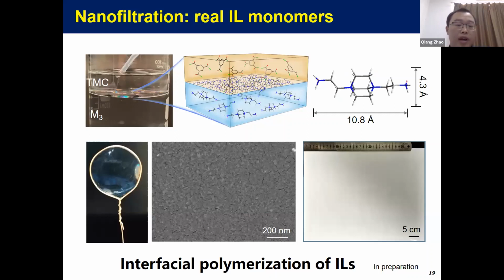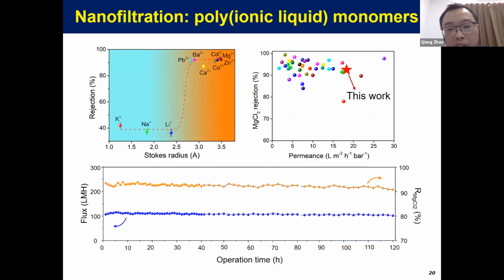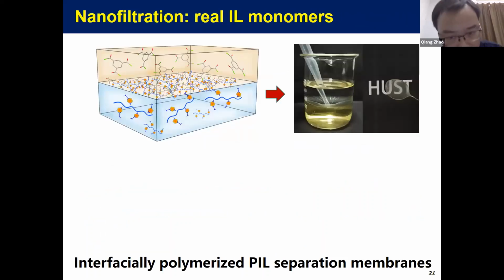I hope they can be published in the near future. We also expanded the scope of this monomer. In the previous talk, we used this monomer for surface modification, and the ultimate goal for us is to use the monomer as a real monomer for straightforward interfacial polymerization. We are right on the way, but we are now able to figure out some of the useful structures for this purpose. And the membrane, as you can see right here, shows a good combination of flux and selectivity. And the important thing is that it is not made by surface modification. It is made by straightforward interfacial polymerization.